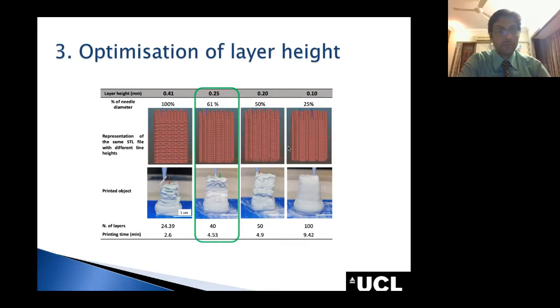When we put the layer height too low, we can see on the right side that the material is too extruded and the printing time is dramatically increased. Therefore, we found that 0.25 millimeter was the optimal layer height for this application.